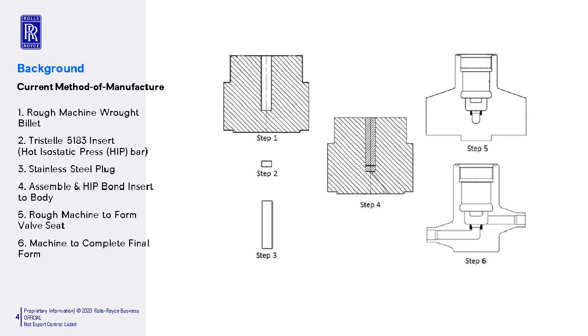This then goes through a second hip cycle, which actually bonds that Tristelle to the 316 material. Step 5 is around machining the internal profile of the component and including the main seat. And then step 6 is around the final machine of the external form. And this same process is used for the back seat when we're producing the bonnet component as well.